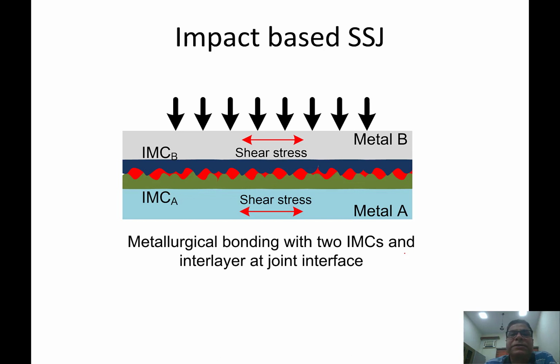Another is the magnetic pulse welding process, where electromagnetic force is used to ensure a high speed and high force impact between the two components to be joined. This in turn leads to micro level interfacial deformation at the interface, and in order to minimize the harmful effect, sometimes we add a filler at the interface. The red one is indicating the filler, and on this side the two are indicating that they are forming some kind of IMC on both sides due to the interactions between the two.